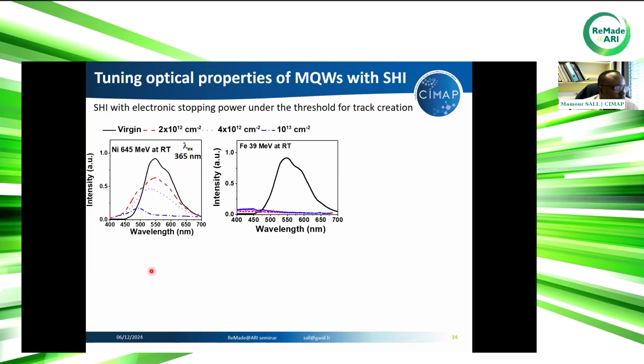So these are photoluminescence spectra of the multi-quantum well irradiated by swift ions, here with nickel and iron ions. What we can see here, the black curve is the spectrum of the non-irradiated material. After irradiation, we lose the luminescence of the material. It decreases as we increase the irradiation dose for nickel ions. For iron ions, we completely lose the luminescence even at the lowest irradiation dose.